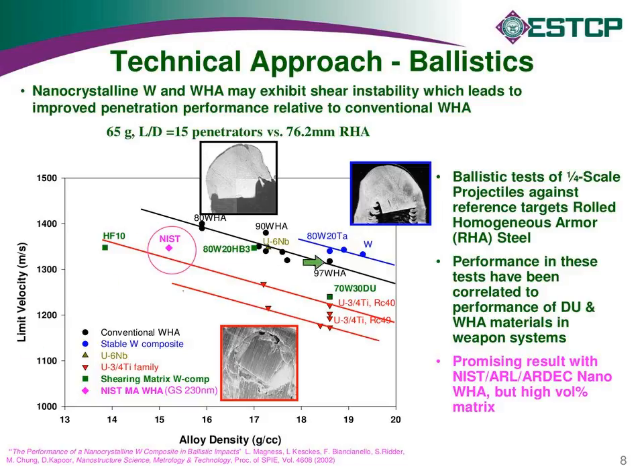those are all conventional tungsten heavy alloys. As you go from an 80% tungsten nickel iron to a 90% to a 93 to a 97%, as you go up in density, the rod gets a little shorter, but it also shrinks in diameter, and the mass to presented area of that projectile shrinks down. So you see this general trend that the limit velocity drops: it takes less energy to get through this 3-inch RHA plate with the higher density material, and that's your typical trend line. Those are all mushrooming type tungsten heavy alloy materials like you're seeing in that little box there.